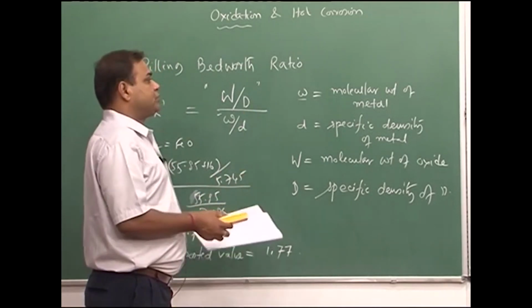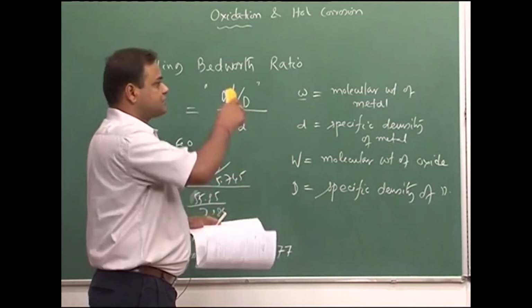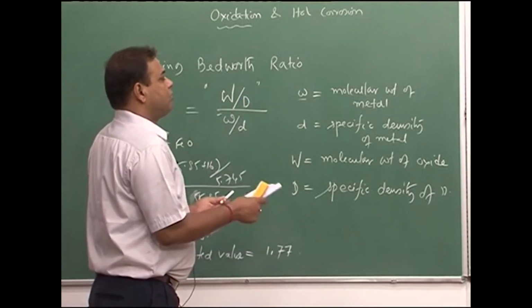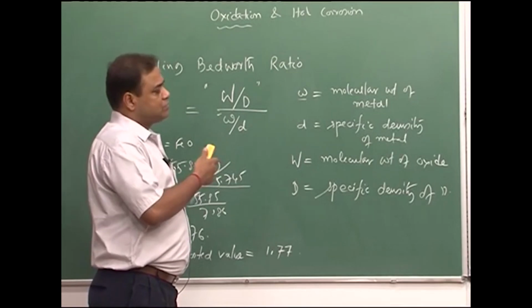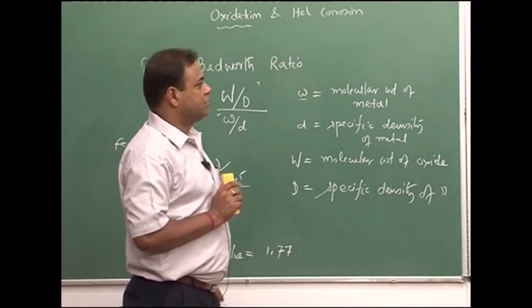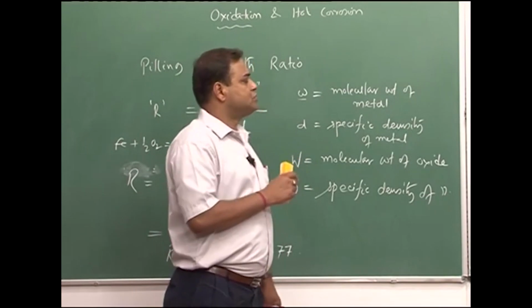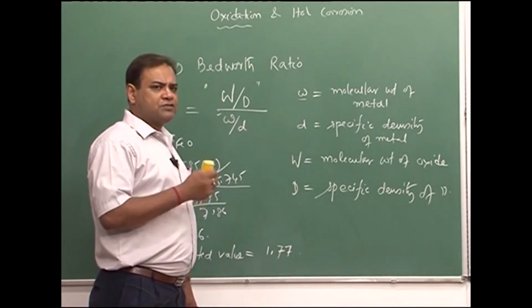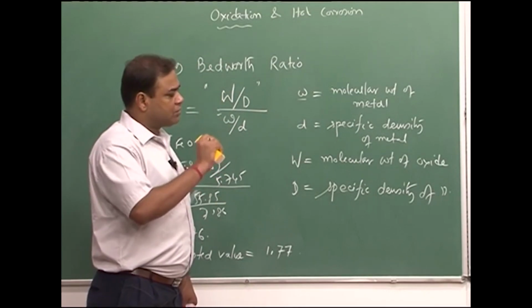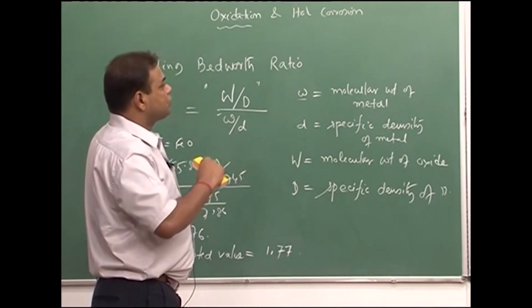that means if we have an oxide layer, oxygen has to diffuse through the oxide layer, or metal ion has to diffuse out through the metal oxide. Later, this has been understood, that there would be diffusion of metal ion or oxygen ion through the metal oxide. That is how the oxidation goes on.